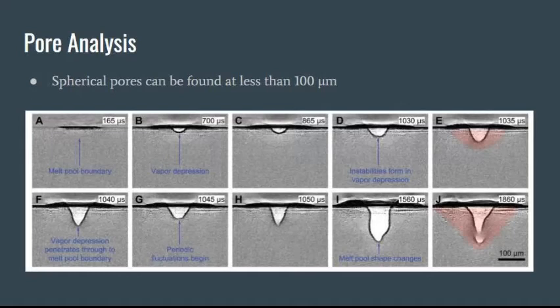You can see that in slide A here, the melt pool occurs. That's when the melting material happens. Then the vapor from that material starts expanding into our base model right here in slides B through F. And once that vapor collapses and is extracted out of the model, that pore is left in its place, weakening the model and leading to a poor surface finish.